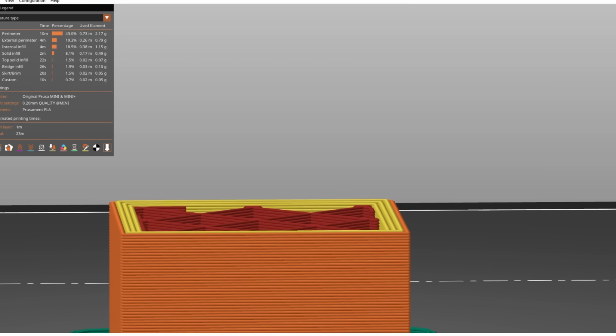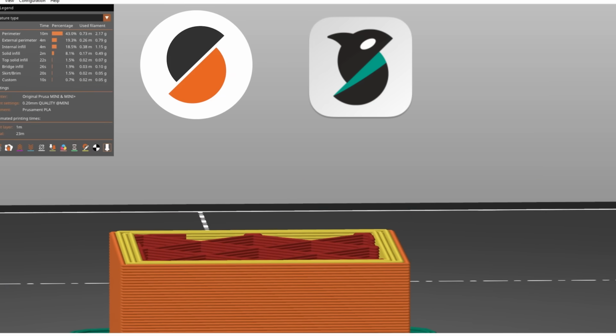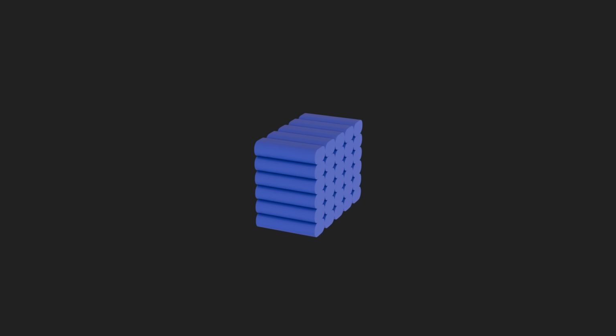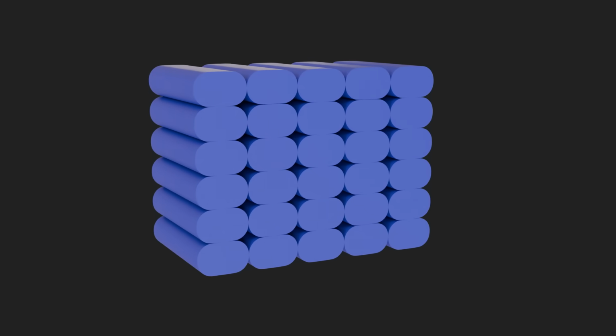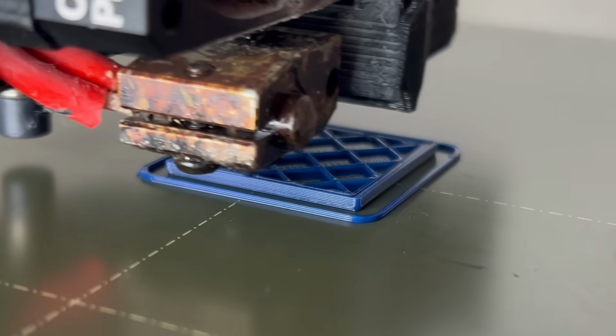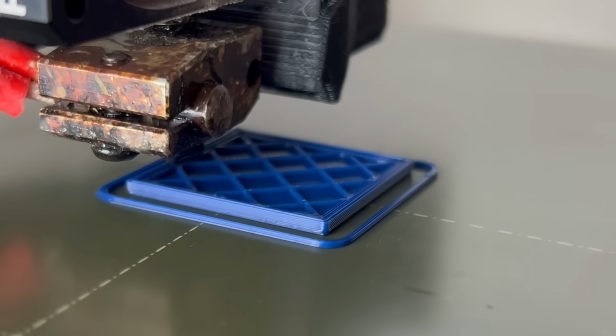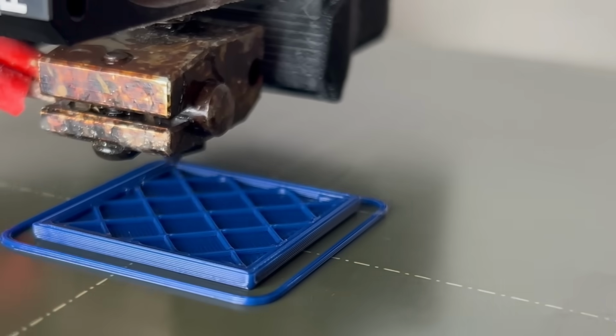I made Bricklayers available for PrusaSlicer and OrcaSlicer, and you can use it now. Bricklayers are a way to make 3D prints stronger in the set direction by interlocking the layers. For that, I coded a postprocessing script that shifts every other wall up half a layer and compensates the first and last layer height. You also have the option to set an extrusion multiplier on the shifted layers to probably gain a little bit more strength.